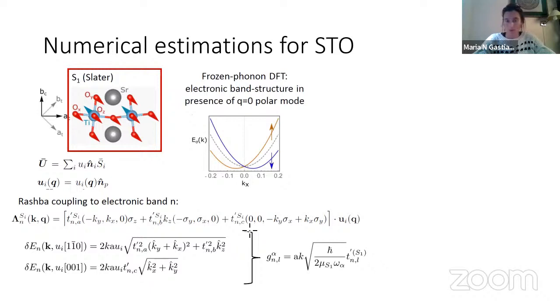And then what happens to these modes, what one expects, as I said, is that the bands should shift whenever you are along a direction that is perpendicular to this polar displacement, because when it's parallel to the polar displacement, there is no pseudo-spin split. And we do know from this model what the form of this pseudo-spin split should be like. First of all, it's going to be linear in K. This is Rashba-like. And then depending on the direction of momenta, you will have the different components of the coupling shifting the two pseudo-spin up and down bands.